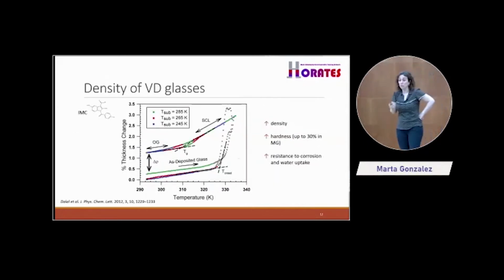But these glasses have other properties, I told you. For instance, if we go to these very ultra-stable glasses, these special conditions, we get very dense glasses. These are our measurements from this group in the US that we're starting using, when discovering the ultra-stable glasses. And what you see is that we start from this glass here, okay, this is the as-deposited glass. These are two different glasses or three different glasses. We heat it up. These are measurements of density, of thickness, but this is done with ellipsometry. But from that we get density, okay?